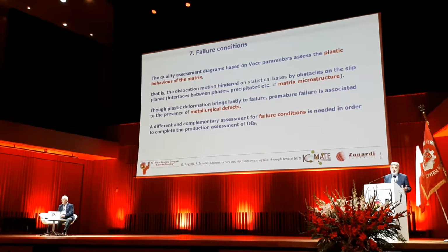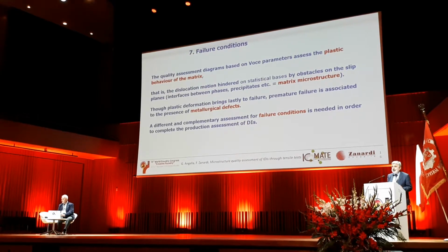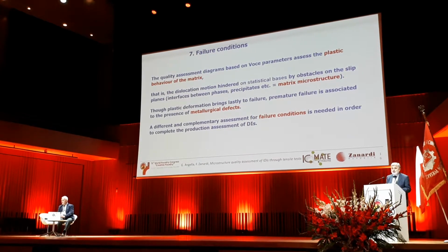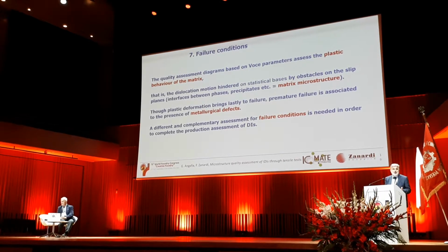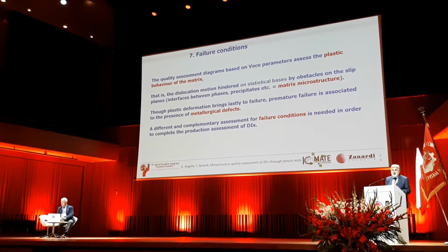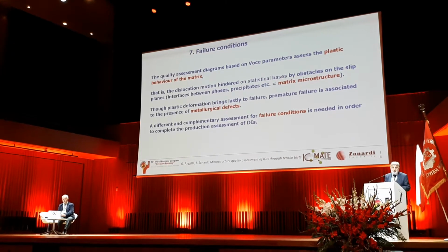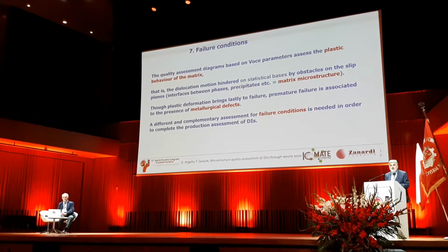Because in the uniaxial tensile test, the small defects drop the elongation very significantly. This is not a question of material quality, but a question of the soundness of the casting.